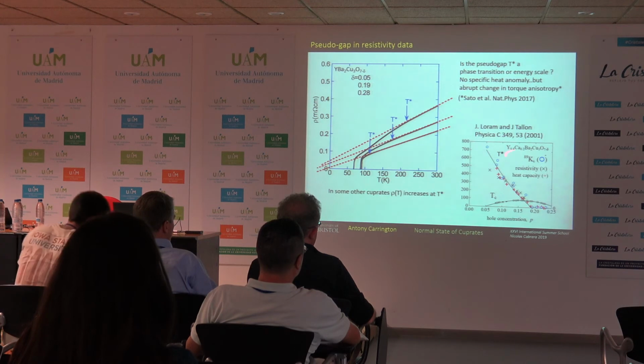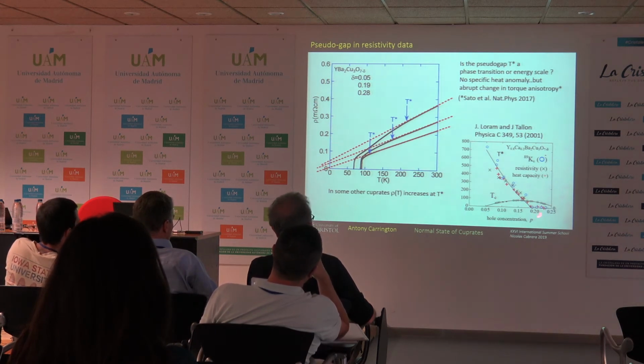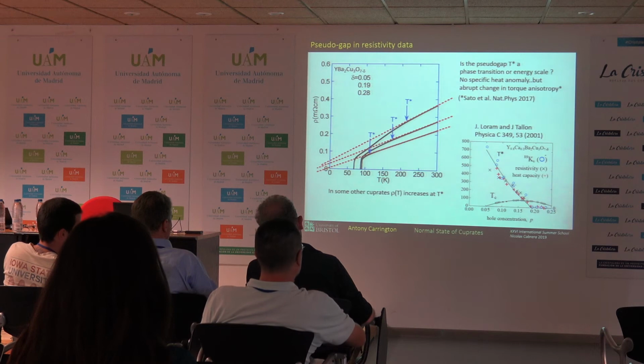So, for example, you can see a depression of the heat capacity, the gamma, at about the same temperature. The Knight shift was historically the place where it was identified first. You see a downturn in the Knight shift. And all of these things seem to determine a common scale. Now there's been some debate over the years as to whether or not this is actually a phase transition or is it just an energy scale.